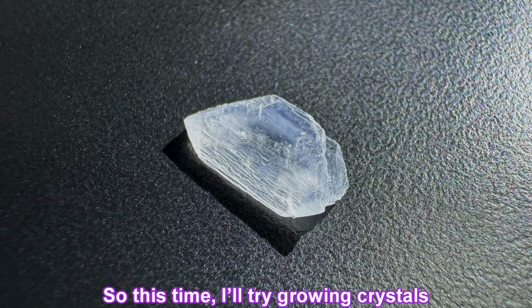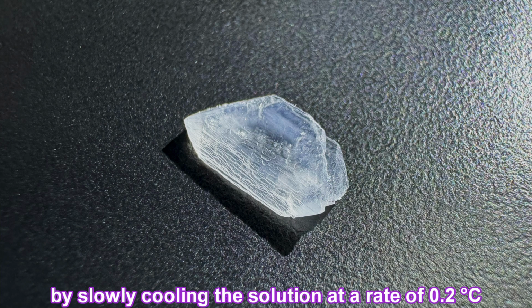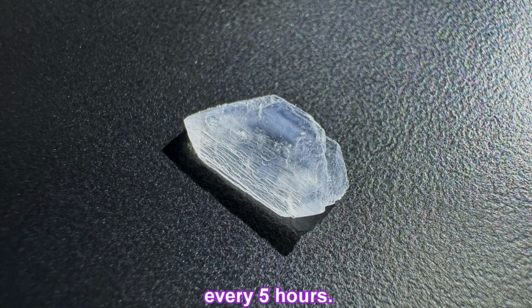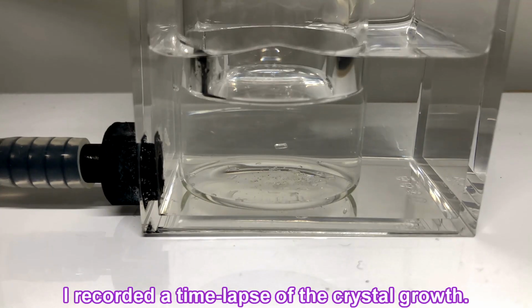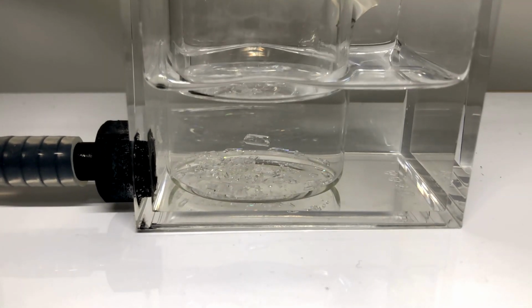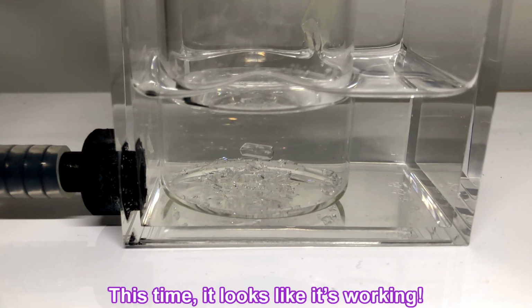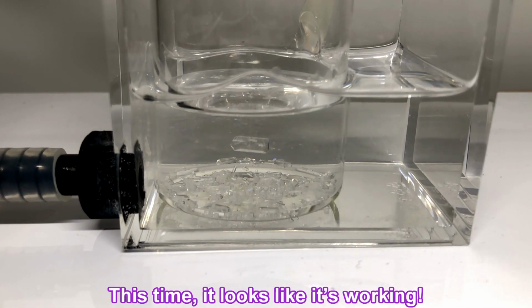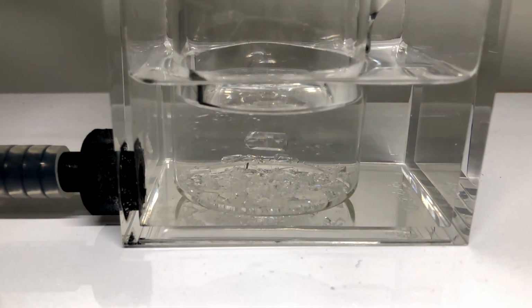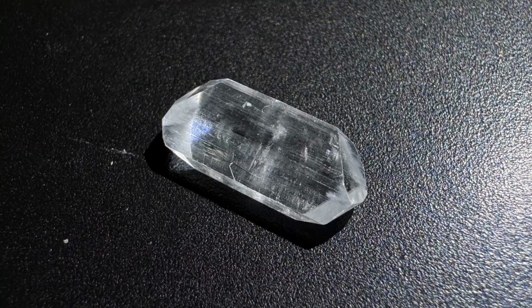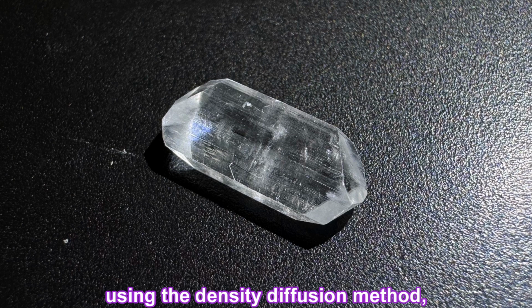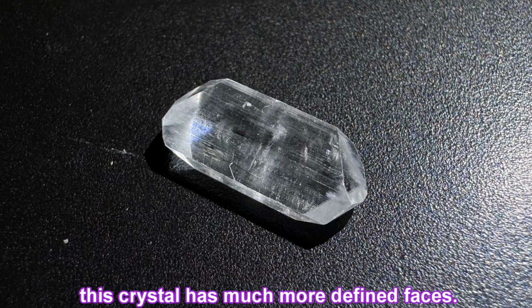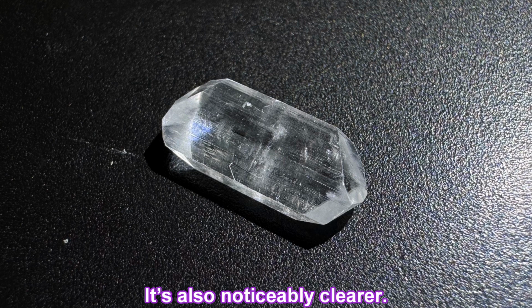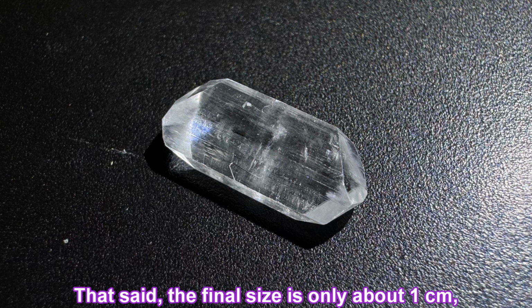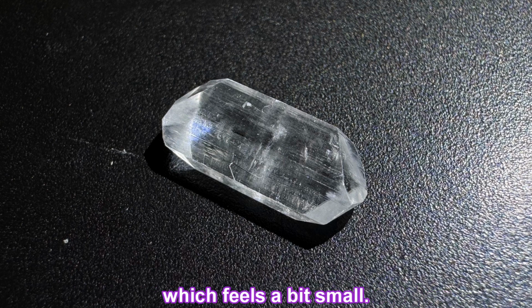So this time, I'll try growing crystals by slowly cooling the solution at a rate of 0.2 degrees Celsius every 5 hours. I recorded a time lapse of the crystal growth. This time, it looks like it's working. And here is the final result. Compared to the one grown using the density diffusion method, this crystal has much more defined faces. It's also noticeably clearer. That said, the final size is only about 1 centimeter, which feels a bit small.